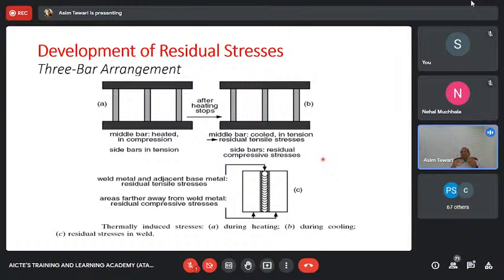But once it melts, there are no possible stresses which a liquid can handle, and thus the liquid starts flowing, and you now have 0 stresses. Why? Because the central rod is completely molten and it cannot transmit any stresses because it is a liquid. And because that is a liquid, the other two supporting rods don't have to push anything further as well. So the moment you have melting of the central rod, all the residual stresses disappear. All the stresses disappear. I won't say residual. It's not yet residual in that sense, if I may say. So all the stresses disappear.